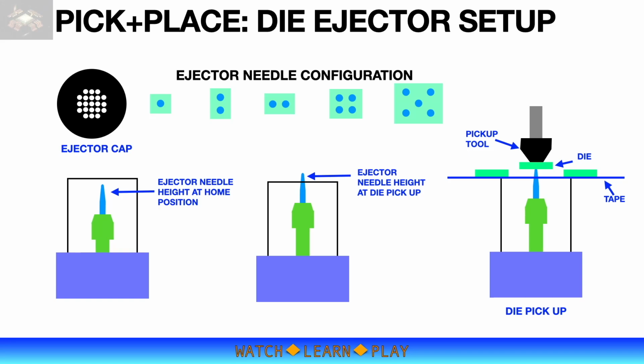Ejector needle pushes the die up from the mounting tape at a height of approximately 1 to 1.5 times die thickness. If the die is not cleared at the proper height during pickup, it is likely to hit the adjacent die once the bond arm moves to the bond position.